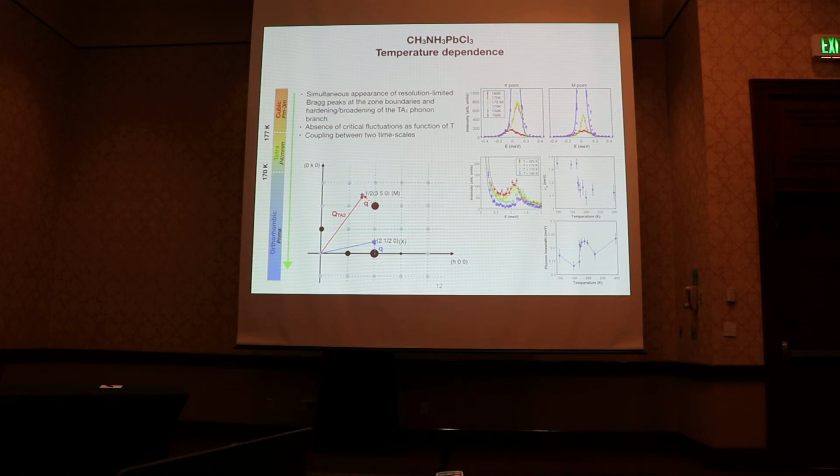So this shows that there's a coupling between the dynamics at the zone boundary and the dynamics at the zone center. The dynamics at the zone boundary is associated to the molecular dynamics, and the zone center is associated to the inorganic framework. Also, these are associated to two different time scales. This is especially evidenced by the jump in the phonon line width here.